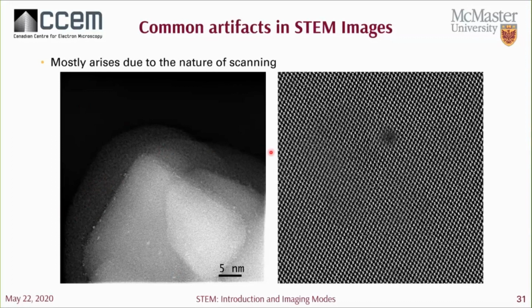And also, if you're working with a sensitive sample, sometimes holes can be formed within just a few seconds, if not even sooner. So you'll have to take that into account. Like this hole isn't a good representative image of your sample.